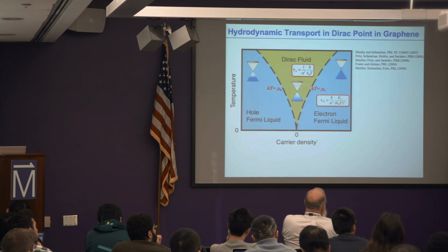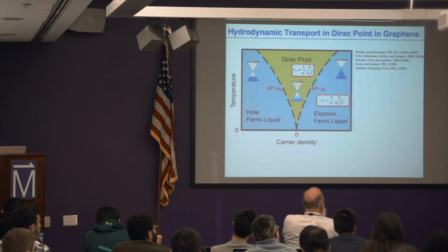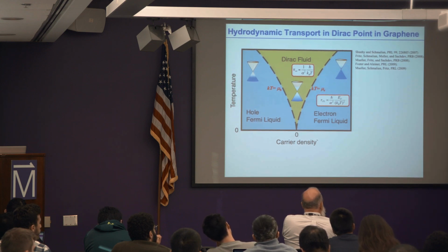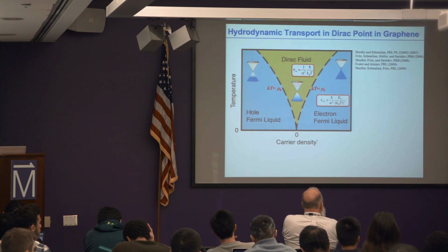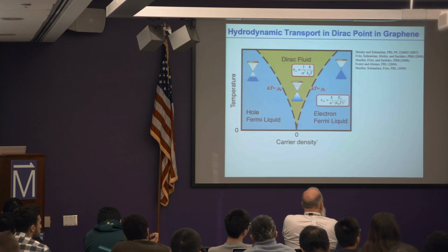There is some experimental evidence that alpha, even without any additional dielectric screening, at certain frequencies is larger than 1, like 4, 5, or even 10. It depends on the experiments, so there is a range of uncertainty about the precise number. But it is clear that this becomes an order 1 quantity in typical situations, unless you are surrounded by a very strong screening medium, such as an STO type of substrate, or metal gates really nearby. Unless in that type of situation, alpha is an order 1 quantity.